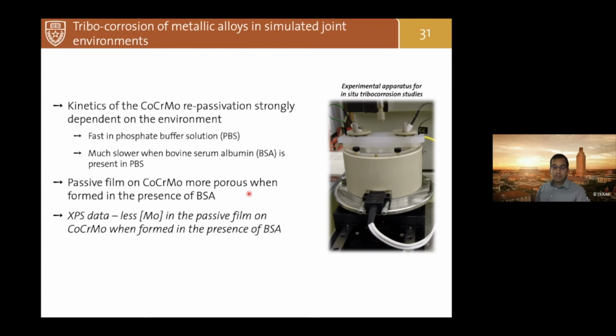How and why does it happen? We are a surface analysis group, and we performed preliminary XPS measurements on this, which indicated that the passive film, the oxide film created on cobalt, chromium, molybdenum, formed in the presence of albumin, contains much less molybdenum, most probably because of the binding of molybdenum with the bovine serum albumin. Something that we are looking at now through the analysis of the liquid that is left at the end of the experiments.